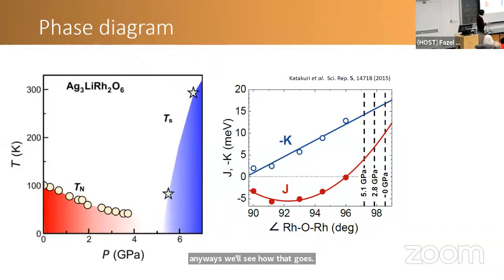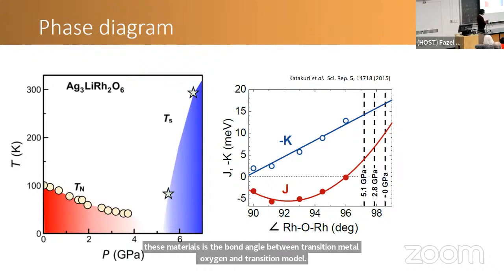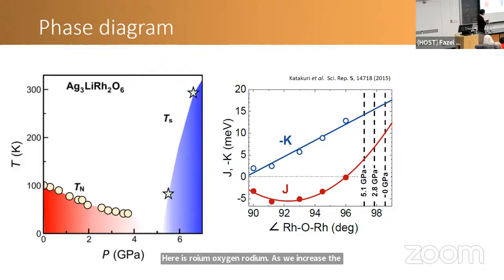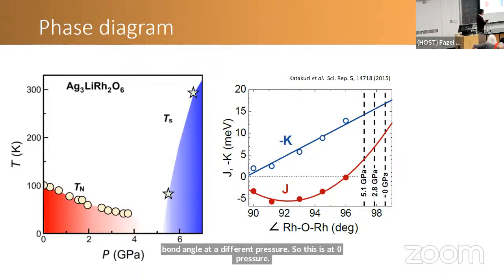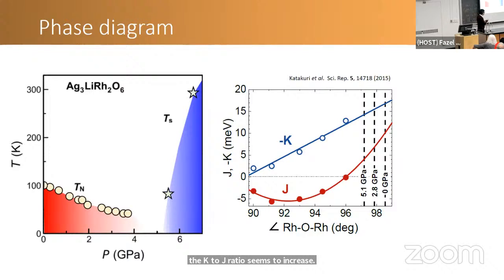And of course, based on the changes of the structure, we found that, so the lines here, they show the bond angles. Remember, the main thing that we are tuning in these materials is the bond angle between transition metal, oxygen, and transition metal. Here is rhodium, oxygen, rhodium. As we increase the pressure, these lines show the bond angle at different pressures. So this is at zero pressure. Then we go to 2.8 and 5.1. As the bond angles change, the K to J ratio seems to increase. This is a quantum chemistry calculation for lithium rhodate, not silver lithium rhodate, but it's a relevant calculation for this material.